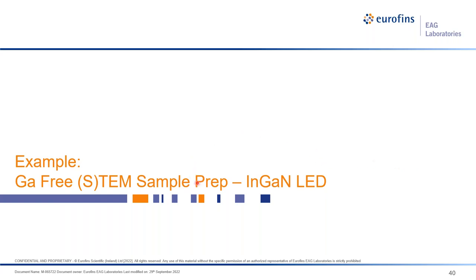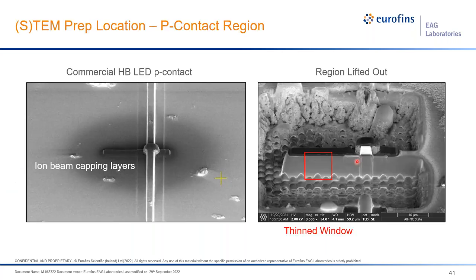So getting away from three-dimensional volumes of material and trying to track, let's say, structure and really understand three-dimensional structure, we can also use the P-FIB for doing gallium-free STEM sample prep as well. This is an example using that same commercial LED from before, but now in this case, we're going to explore a region near the P contact.